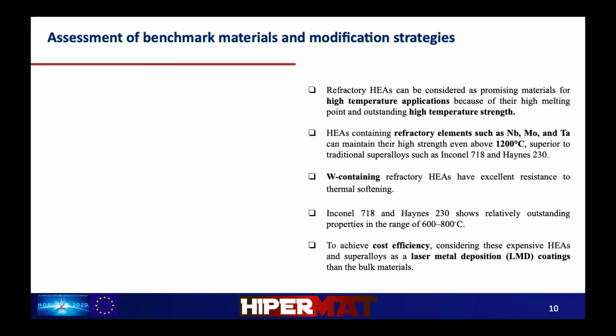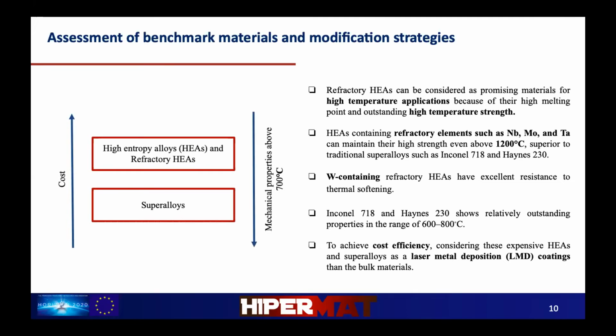Whereas, on the other hand, the superalloys show exceptionally outstanding properties over the range of 600 to 800 degrees Celsius, and can show better properties with some modifications. Apart from this, it is very essential to consider the cost efficiency, and high entropy alloys tend to be very costly with respect to superalloys. And therefore, for Hypermat, the high entropy alloys and superalloys are considered as laser metal deposition coatings rather than the bulk material.